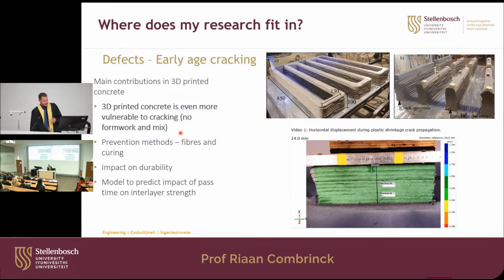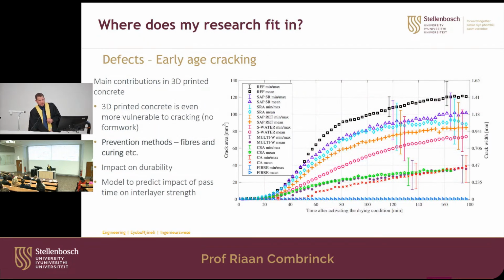So we were some of the first that actually tested this, and we also then looked at ways of preventing it. So if you add fibers, that's very effective. This shows the crack area with time, and as you add fibers, you can see you reduce the crack width to 0. And then also water curing and curing agents. Also, these are, I think, the red and the purple dots there. You can reduce the cracking versus no curing agents. So there are some remedies that you can use. I'm not going to go into the others. We used it too much now.